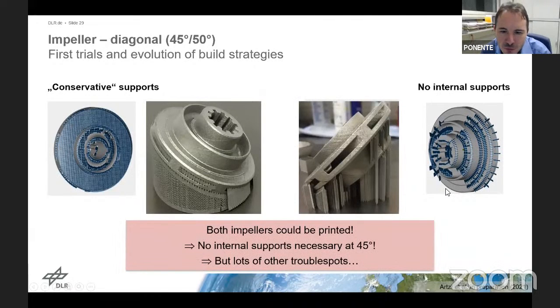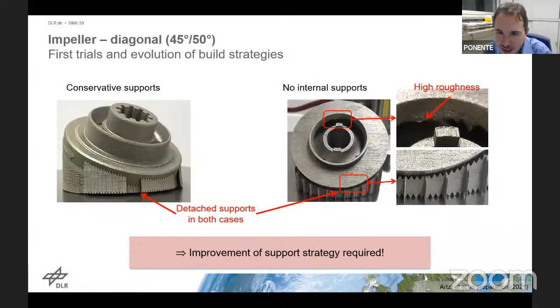And even with these 2 support strategies, even with this very massive amount of supports on the left-hand side, in the images after processing, you see this front support is bent off. It's ripped off from the base plate. So there are very high internal stresses, and this wasn't successful either. If the supports detach from the base plate, that immediately means you will have distortion in the part due to thermal residual stresses.